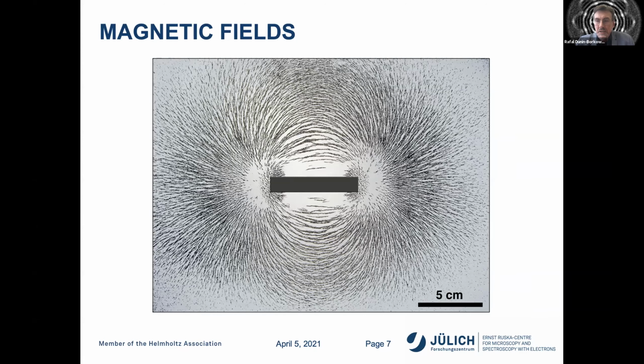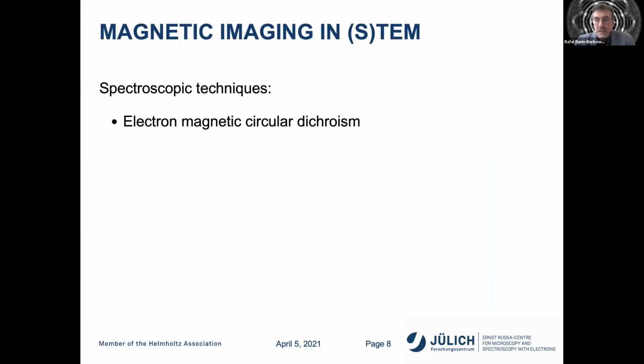This is extremely challenging using any technique, and in particular, most magnetometry techniques, which are carried out on bulk samples, provide relatively little information about the nanoscale magnetic microstructure of the materials. So magnetic imaging in the transmission electron microscope can be carried out using a few different techniques. Some of these are spectroscopic techniques. In particular, in EELS, there is electron magnetic circular dichroism, which is sensitive to the magnetization M. Normally, the magnetization is measured in the direction of the incident electron beam.